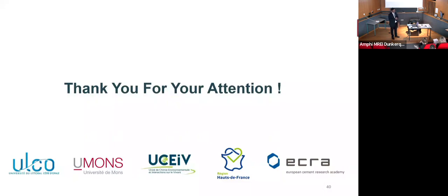Perfect. I would like to come back to the perovskite section, even if you didn't present anything during your presentation. So what was the main reason for studying the feasibility of perovskite materials as catalyst for this reaction? Okay, so generally I first explored a very extensive review of perovskite materials for the NO reduction by CO reaction. So I saw that perovskites could be a good alternative to our mixed oxides as well, because generally perovskites are more stable than the mixed oxides because they are calcined at high temperatures. And our reaction temperatures are lower than the calcination temperatures, so we expect not to have a lot of differences in the material properties during the reaction. So we could expect a good stability for our material.